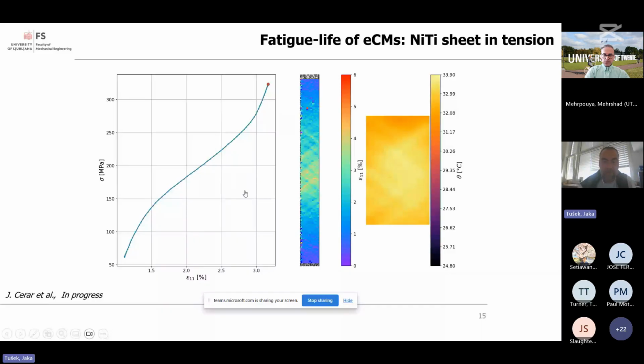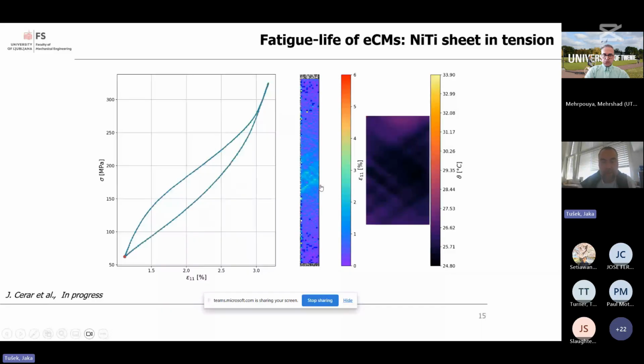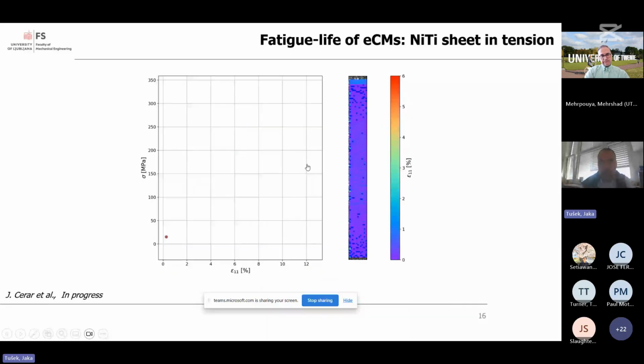You can see that there's local strain up to 5% and adiabatic temperature changes up to 7 kelvins, which is quite promising, but only locally. Of course, if the total strain is larger, then at some point the sample failed due to crack propagation as shown here.